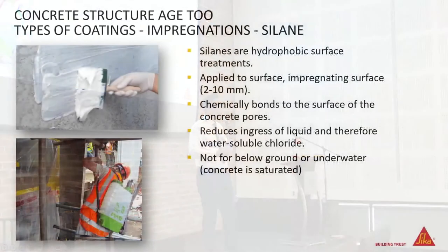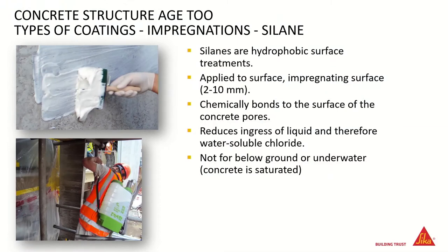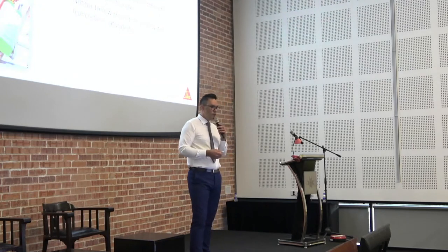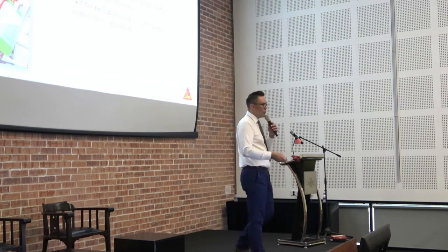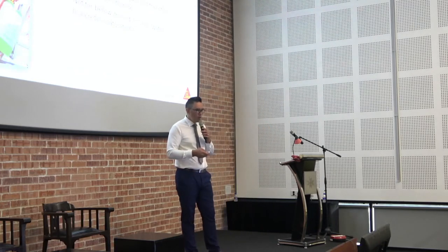The other option is low viscosity or spray-on products. You could use those when you have a large area to get done quickly, because it gives you the freedom of spraying a much broader area. It chemically bonds to the surface of the concrete pores, so that still allows the vapor to come out, and it reduces the ingress of liquid and therefore those water-soluble chlorides and aggressive chemicals. However, it's not much use for underground, because water has time to permeate through as a vapor, as opposed to just repelling and being dispersed.